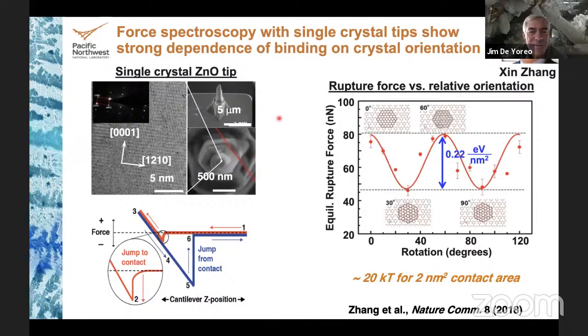Xin Zhang did some beautiful work in measuring the forces between zinc oxide 001 surfaces. In order to do this, he made single crystal AFM tips out of zinc oxide using focused ion beam. And this is a TEM image of the tip. Here's a SEM image showing you what this tip looks like. The way this works is the tip is brought down to the surface. It jumps to contact, and then it becomes repulsive as the tip is pushed further. And then as you try to pull the tip off, it's stuck. So you go to a large negative force. And as you keep pulling, it pulls off of the surface.